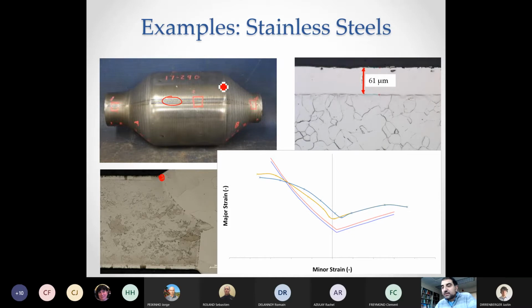Same thing here, if you look at some of these parts, the deformation can be very large during the making of the part. So we had to think a lot about the formability of the material. And I can't show all the data because the company wants to protect that information, but I can show you the relative trend. If you compare to 439 stainless steel or 409 stainless steel, they are given by the blue and the red lines. And this material, the graded material that has the chromium layer on the outside, and the IF steel on the inside has much better formability, as you can see from this forming limit diagram.